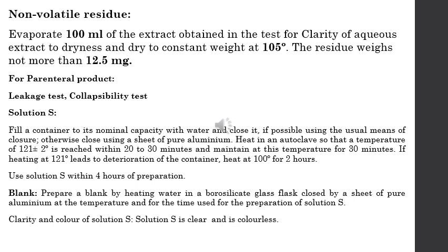For non-volatile residue, we have to take the extract which is obtained from the test for clarity of aqueous extract solution that is mentioned in the previous slide. We have to take 100 ml of the solution, dry it to a constant weight at 105 degrees Celsius, and the residue weight should not be more than 12.5 mg.